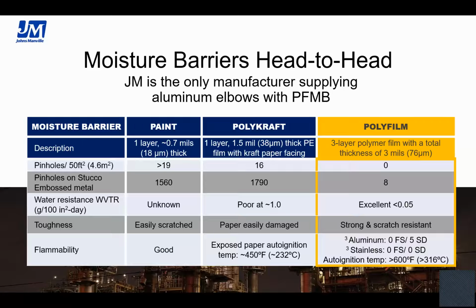The big takeaway from this obviously is the polyfilm results. And I want you to look at the pinhole testing. For the most part, there is testing for pinhole concentration, water vapor transmission, toughness and flammability, but pinhole is kind of the clincher here. There is an ASTM test method for these. Essentially, when pinholes were introduced, polyfilm performs the best in reducing the occurrence of those pinholes. The reason pinholes matter is because every time you have a pinhole, you have an opportunity for water to enter your system. So as much as you can reduce the presence of pinholes, you want to.